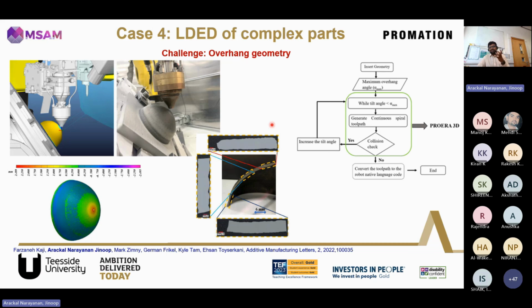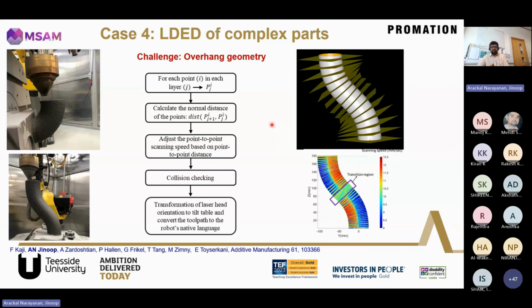So we could see that the dome structures that we built are defect free, and we could also see that the geometrical quality is also very high. This is one of the interesting works that we did and published in Additive Manufacturing Journal, which is on developing overhang geometry like a double bent pipe using additive manufacturing.